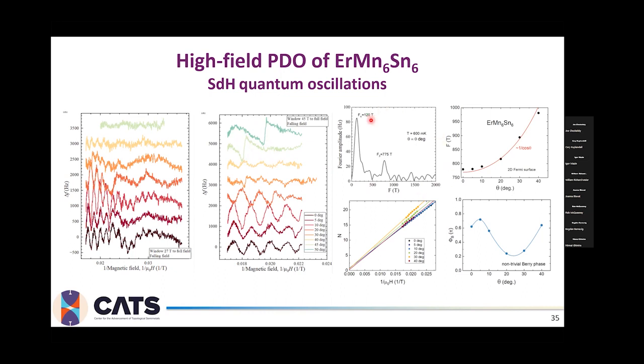When I take the Fourier transform at 0 degrees, I can see two different frequencies, one at 120 Tesla and the higher at 775 Tesla. By analyzing how the frequency changes with angle, I was able to see that it is following a 1 over cosine theta behavior, which suggests that this is a 2D Fermi surface. And by creating the Landau fan diagrams and extracting the Berry phase from the intercept, I was able to say that it has a non-trivial Berry phase.